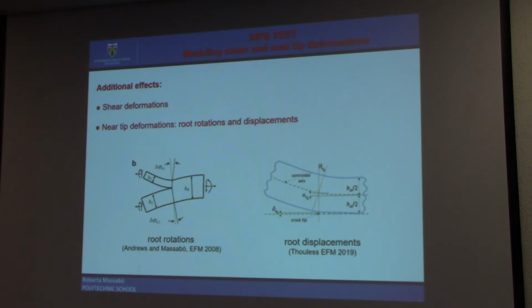And if the crack is long enough, they can be defined as a linear function of the crack tip forces, moment and force resultant, through some compliance coefficients. And the values of the compliance coefficients can be found in many papers in the literature, both numerical solutions and, recently, also an analytical solution by Konstantin Ustinov.